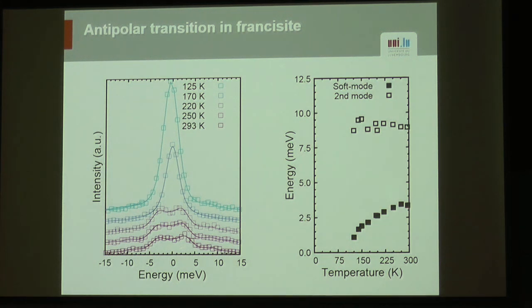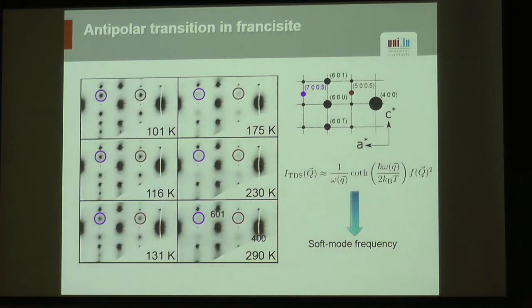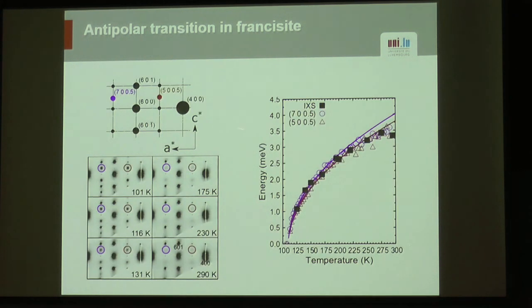Now again, this is a bit frustrating because we're resolution limited, so in order to get a more accurate picture, we also went to thermal diffuse scattering. Here the principle is that you record those maps in reciprocal space, and you follow the diffuse scattering intensity at the Z point. If you assume that all this diffuse intensity, which is growing here, comes dominantly from one soft phonon, then there is quite a simple relation between this intensity and the frequency of the said phonon. So this is another way to get back to the frequency, up to some scaling factor. But since we have the inelastic measurements, we can scale this.